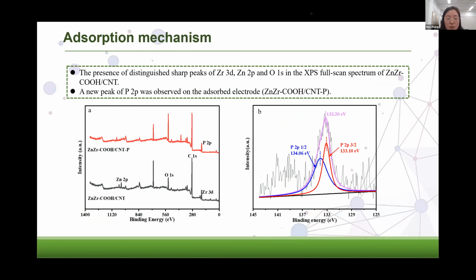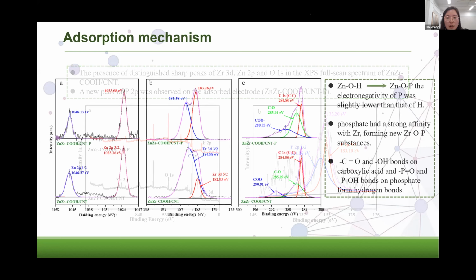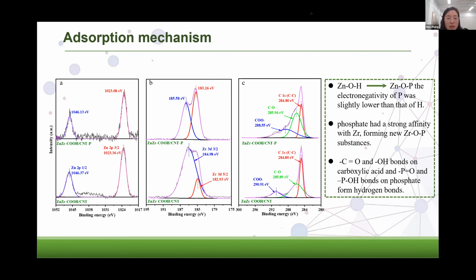Next, we further studied the adsorption process of the electrode and propose a possible adsorption mechanism. In the left figure, there are distinguished sharp peaks of zirconium 3d, zinc 2p, and oxygen 1s in the XPS full spectrum. And in the right figure, a new peak of phosphorus 2p was observed on the adsorbed electrodes. Besides, after phosphate adsorption, the binding energies of zirconium, zinc, and carbon decrease or increase to a certain extent. This is because of inner sphere complexation and coordination exchange, which change the density of electron clouds around atoms, resulting in the increase or decrease of binding energy.